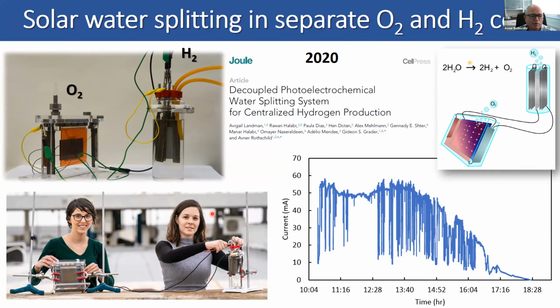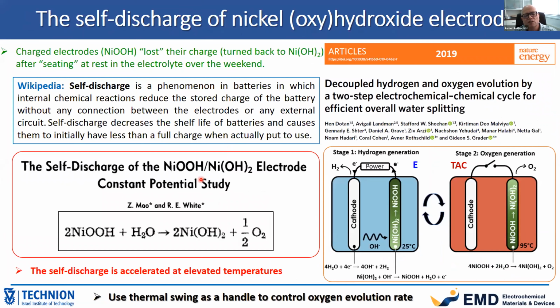But then we found out, actually Abigail found out while doing this measurement, a very interesting phenomenon. She noticed that there is a process of self-discharge. So how did she notice this? When she did the experiments during the weekdays, she always had repeatable conditions. But over the weekend, she noticed that she could not charge as much as she could during the week. And then we understood there is some spontaneous discharge of the charged electrode.